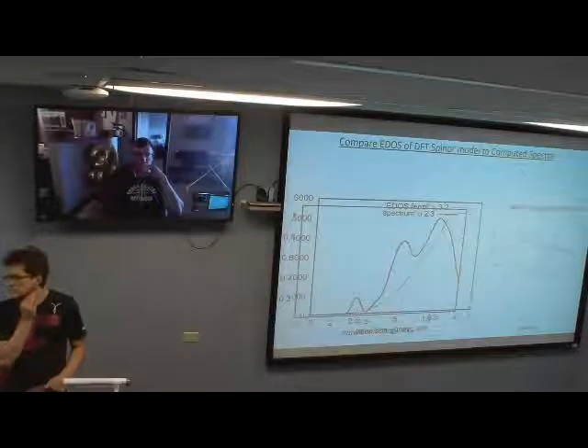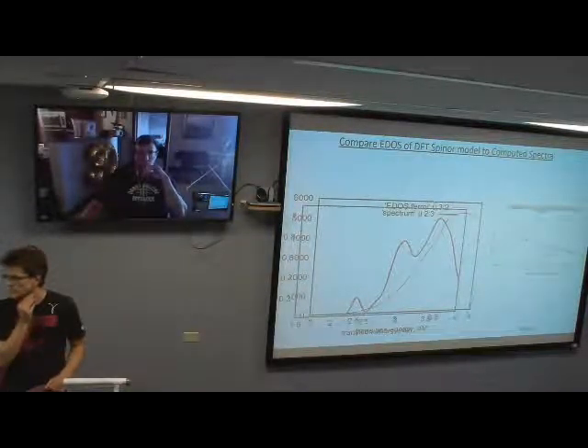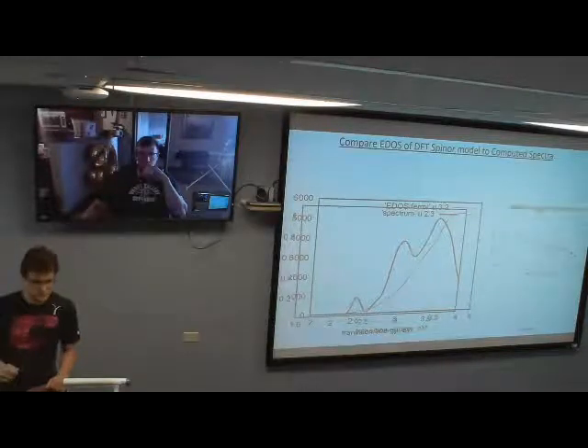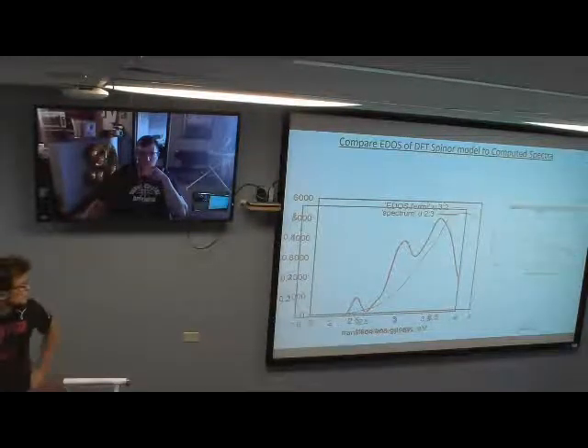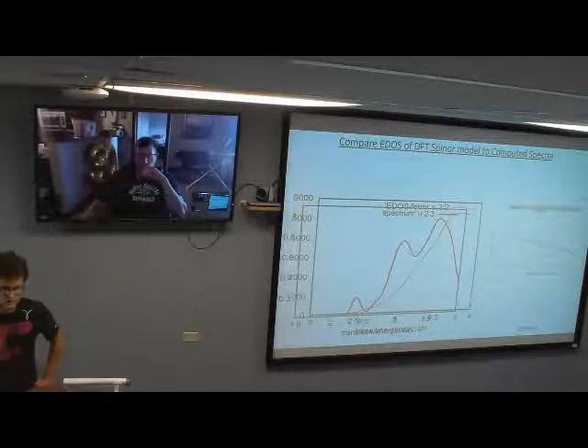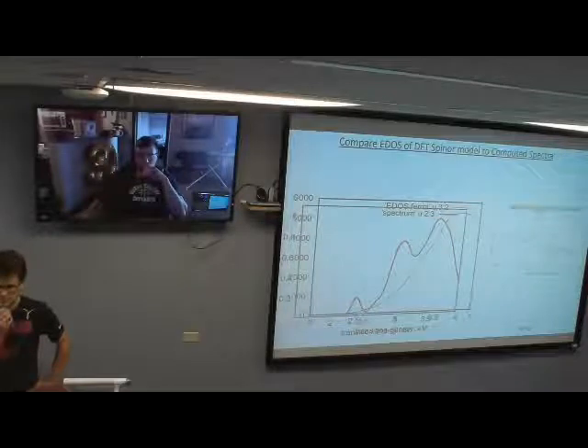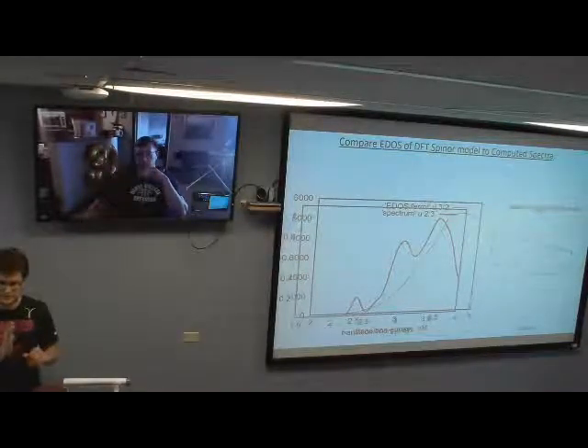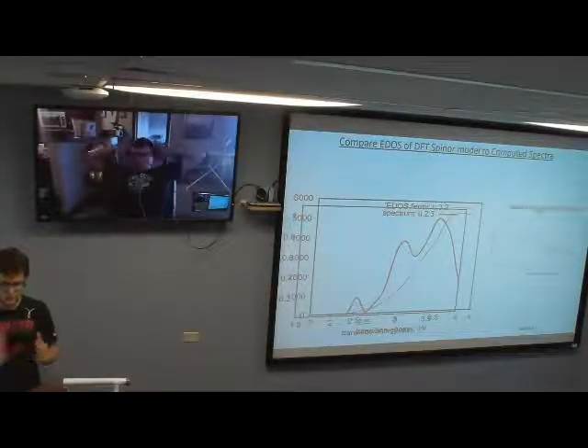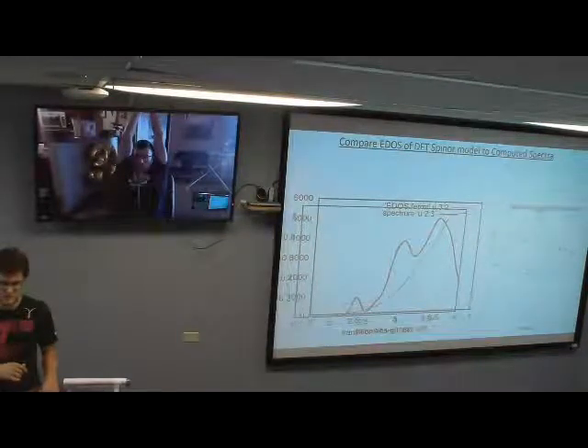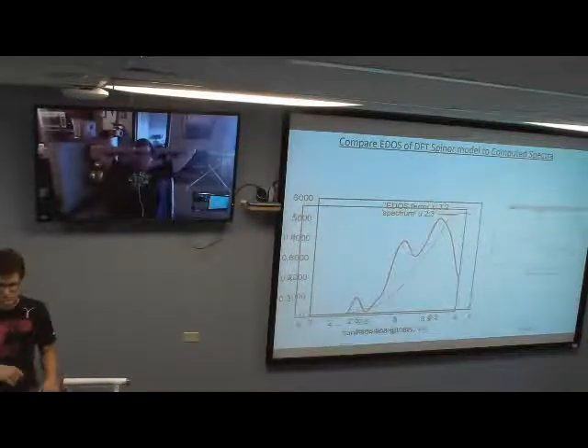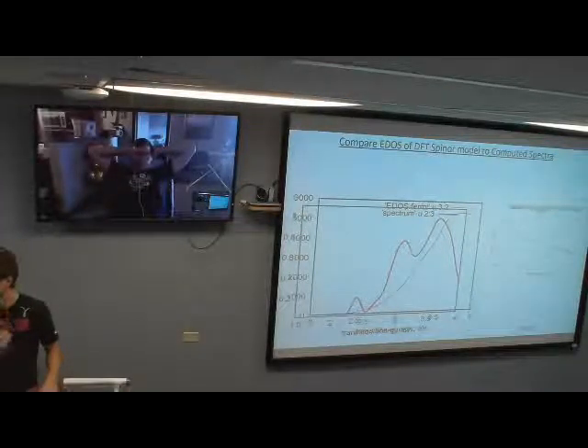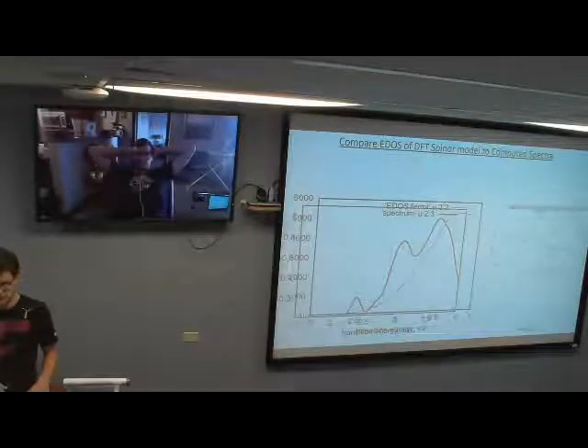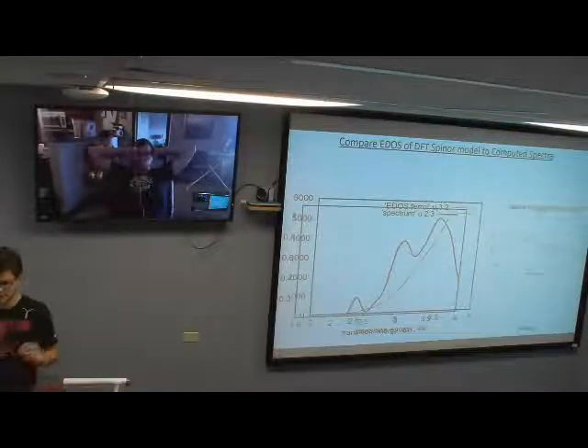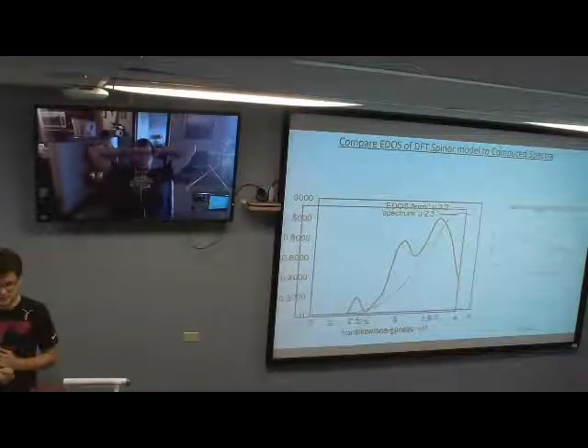Interesting. I thought that was an interesting thing, because I think EDOS is pretty comparable to a bulk absorption, since you have such finely spaced energy states, a lot of them overlap with each other, so most transitions are equally probable in a rough sense. But when you go to confinement, that trend decreases. Your lowest energy ones become higher, and your higher energy transitions become much less likely.